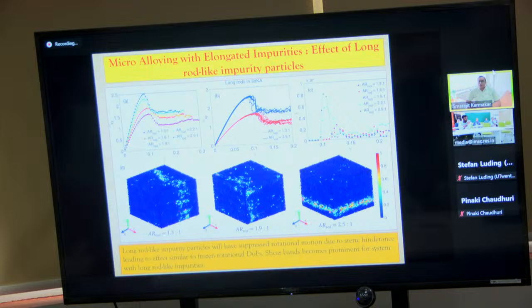It looks like the rods are promoting shear bands in a particular region. But also note that in these snapshots, rods are actually distributed everywhere. It's not that they are all aligned in the shear band. But somehow their presence leads to much sharper shear band formation. Are these shear bands devoid of the elongated rods? No, they are uniformly everywhere. It's not that their concentration increases in the shear band. They are still uniformly distributed in the sample, but somehow the shear bands are much thinner.